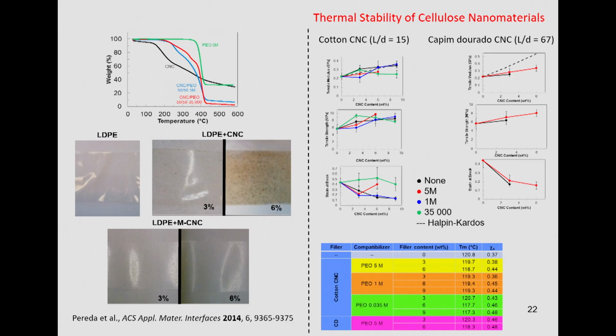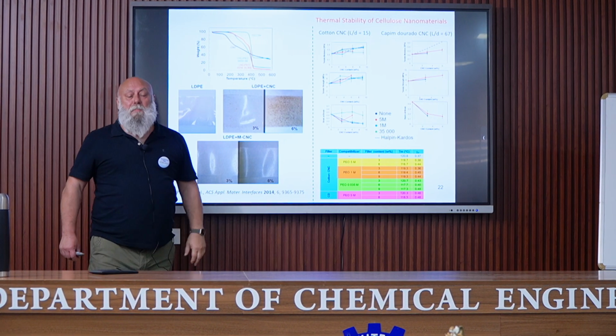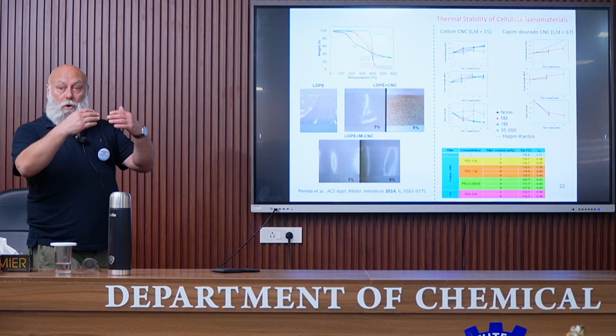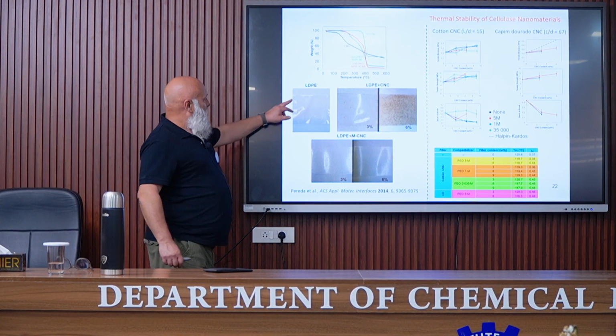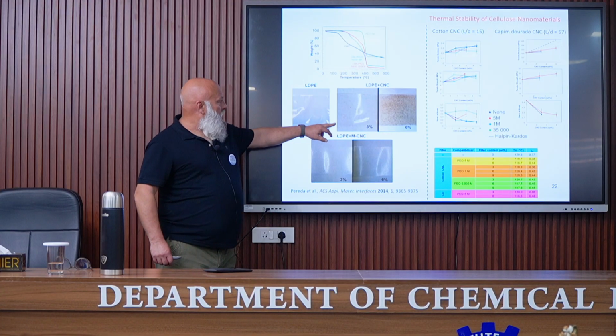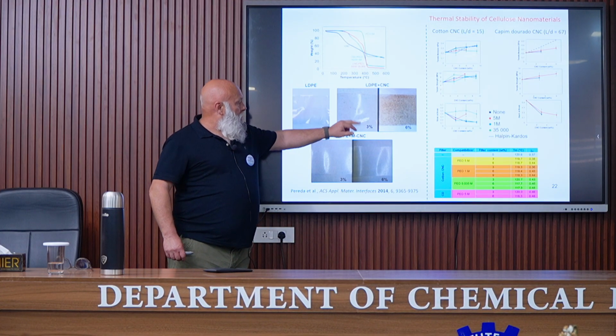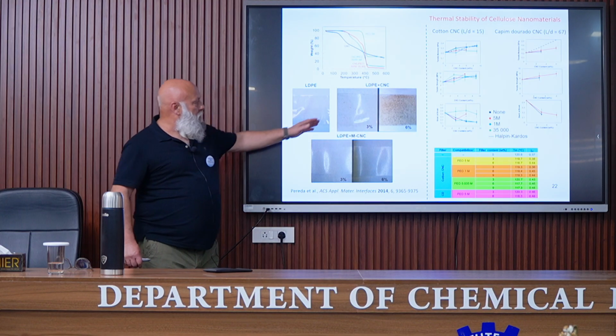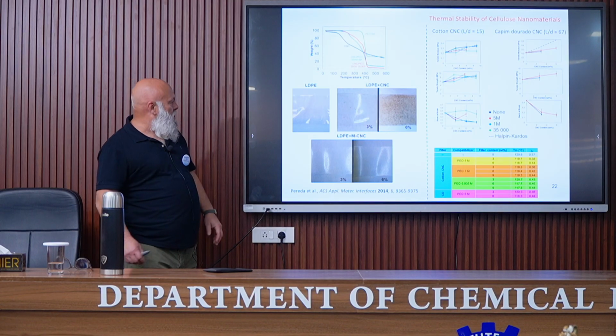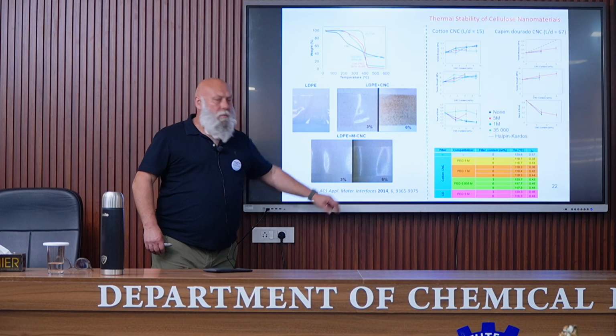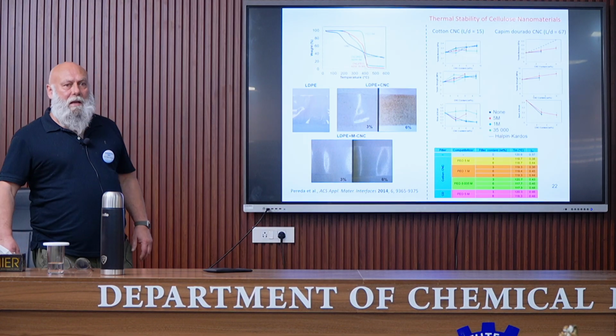So anyway, we checked this, we don't know exactly what happened, and something like 20 years later, we thought, why not use this for extrusion? Because when considering the cellulose nanocrystals mixed with polyethylene oxide, you can see that there is an increase in the thermal stability because of the coating of the nanocrystals. And when using low-density polyethylene, pure polyethylene, or with 3% or 6% nanocrystals, we still have this thermal degradation that can be clearly observed. But when using modified nanocrystals, we don't have this thermal degradation.